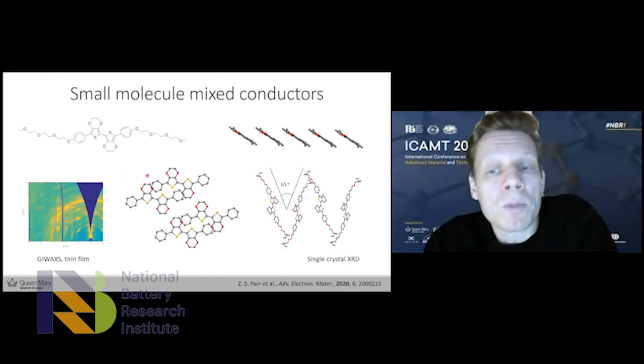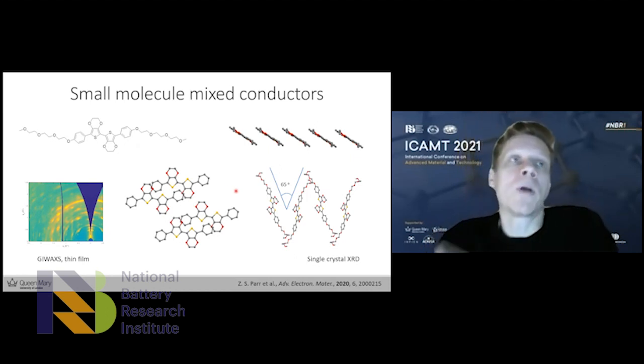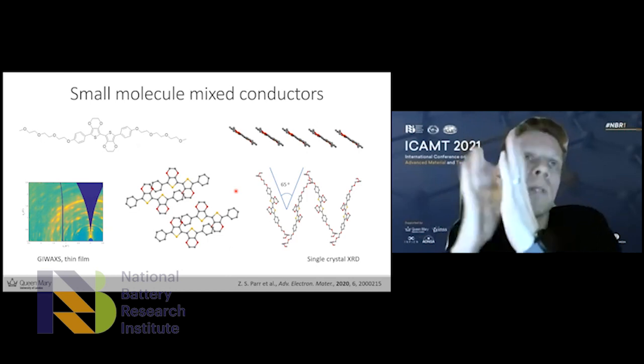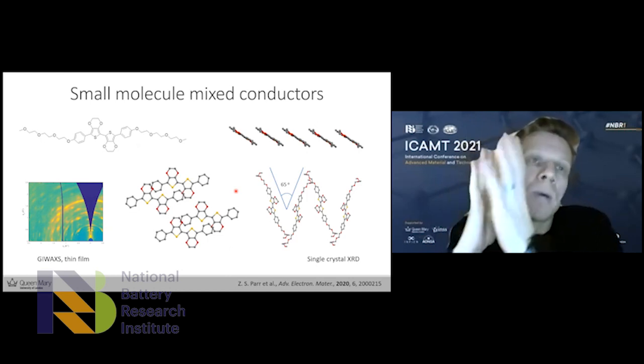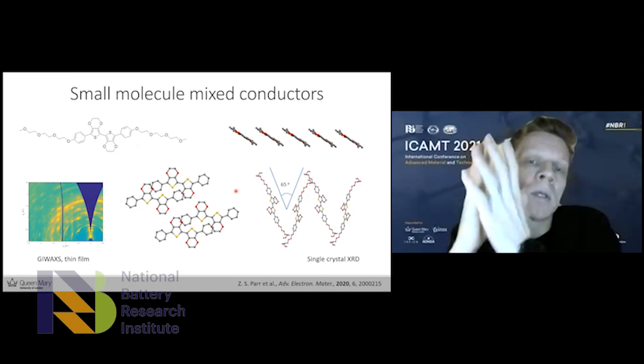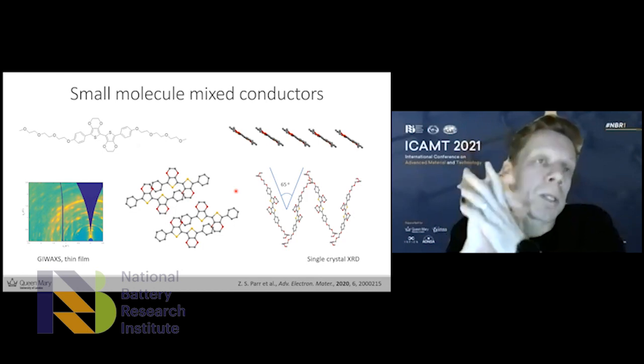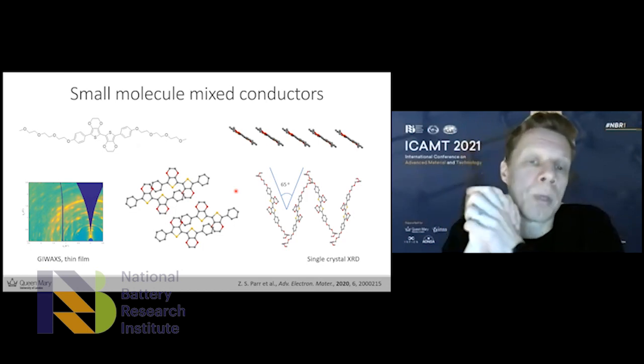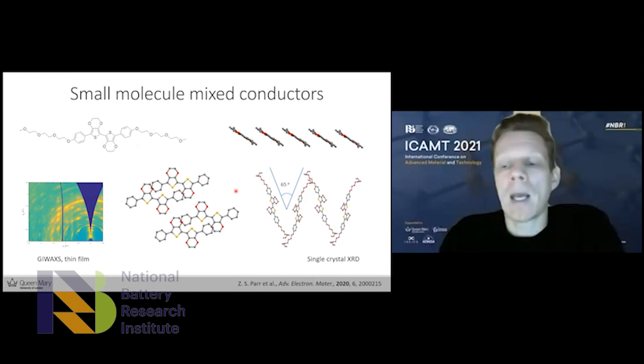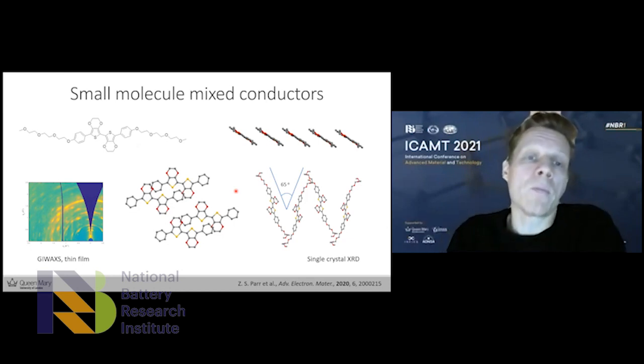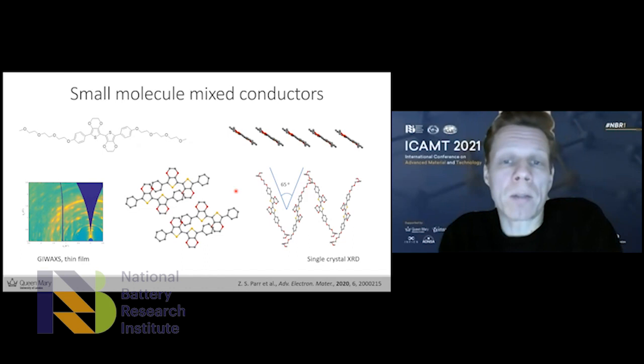Nevertheless, when we did some structural characterizations of this material, we saw that it was extremely crystalline. We managed to get a single crystal structure of the small molecule. And when we look carefully at the single crystal structure, we don't see any close pi-pi interactions, meaning that the charge transport in this crystal is probably not very good. And that actually explains why we struggle very much to get working OECT devices for this material.